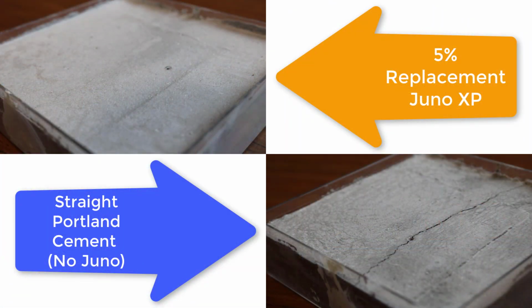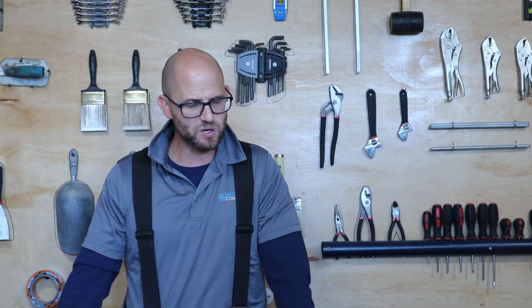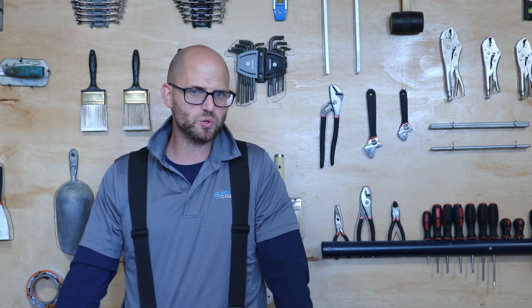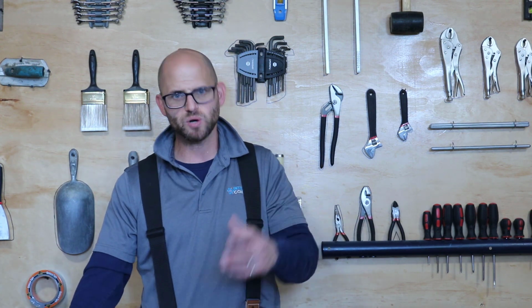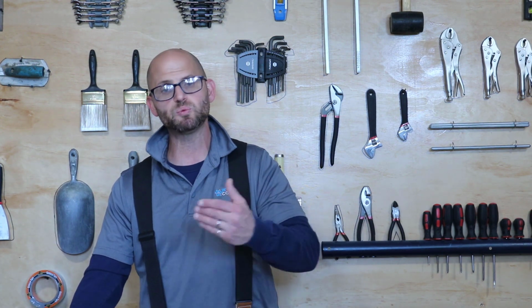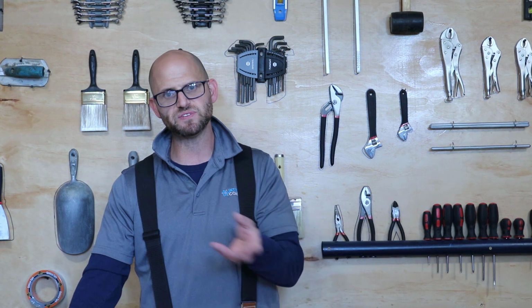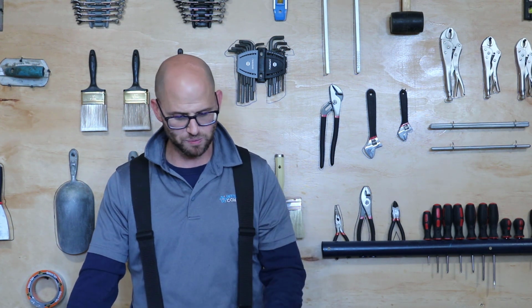So what we've got right now is 2 samples, one which is a straight Portland cement, and the other one is 5% replacement of the Portland cement with Juno XP. Now please bear in mind, normally when we use Juno XP, we're getting a major reduction in total cementitious, like a 20% reduction of cementitious, and then we're putting 5% Juno in and making up that yield with our coarse and fine aggregate. But for our testing, specifically under ASTM C1709, we have to stick to this prescriptive method.